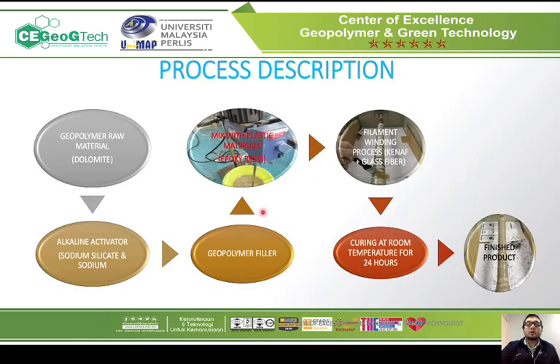So this is the process description for this product. Firstly, the geopolymer raw material that we use for this project is dolomite. Then we mix it with the alkaline activator, which is sodium silicate and sodium hydroxide, to make the geopolymer filler. Before we mix the geopolymer filler with epoxy resin, we crush the geopolymer itself to make a geopolymer filler of 150 micrometers.